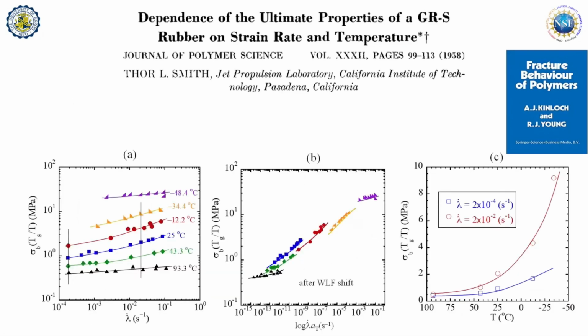We take the very same data and do WLF shifts. There's something going on we don't understand. Basically, if you do the WLF properly, this is the data, not that. And they don't give you a master curve. Of course, the whole burden is for me to explain why that happens. So notice that at different temperatures, at different rates, the temperature dependence is different according to this data.